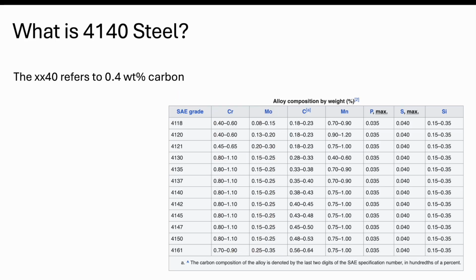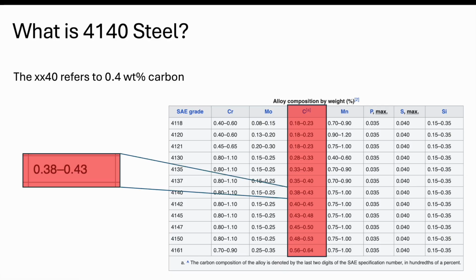The other part of this name is the last two digits. And this holds up in a lot of steel designations with this 4-digit number. The last two digits, here being 40, refer to 0.40 weight percent carbon. If I highlight here the carbon weight percents for various 4100 series steels, you'll see that the 4140 has about 0.4. They always have a variation here because there can be batch to batch variation, but that's the range that we need to have. So it's a 0.4 weight percent steel with chromium and molybdenum.